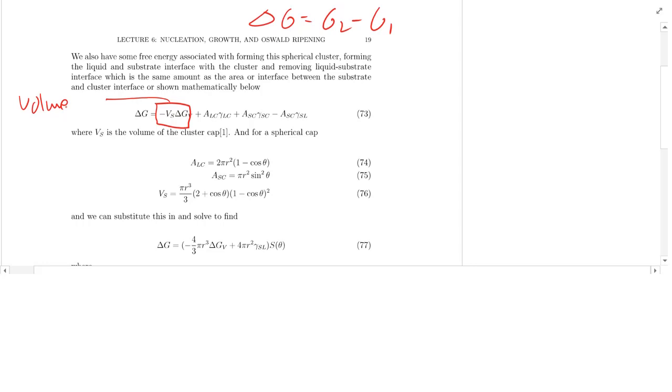Now, we have basically this additional set of additional terms right here. So here, we are going to have the area associated with the liquid and the cluster, the substrate and the cluster, and the substrate and the liquid. So we have to kind of account for all these different areas in the heterogeneous nucleation case.